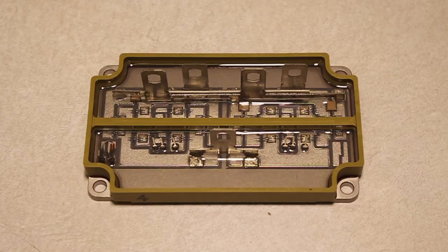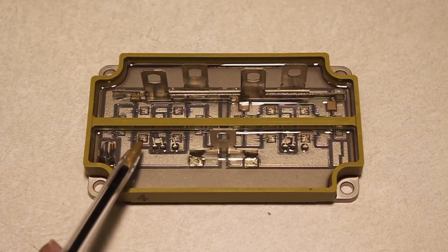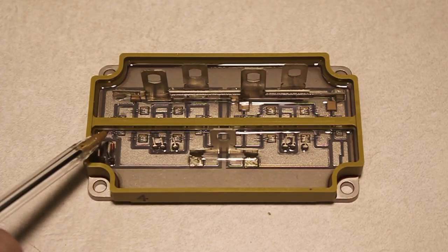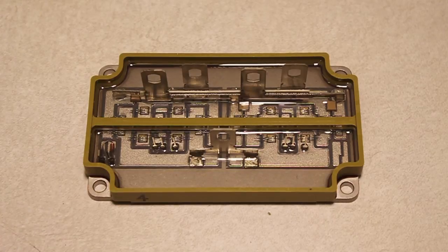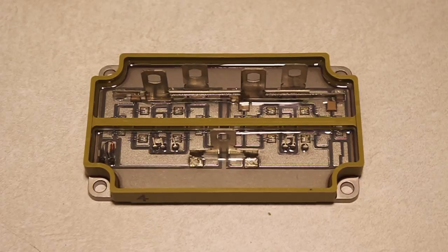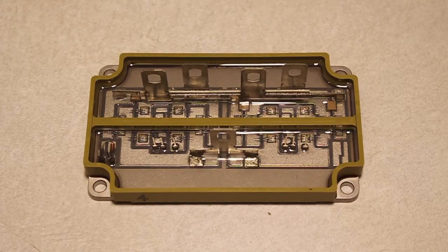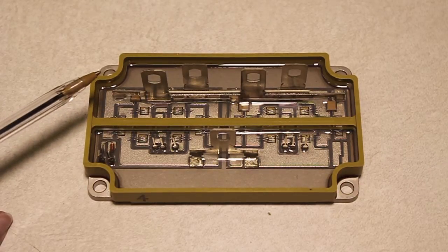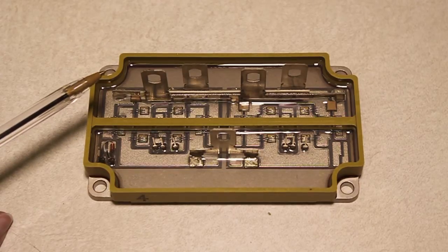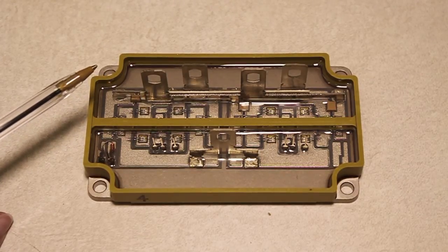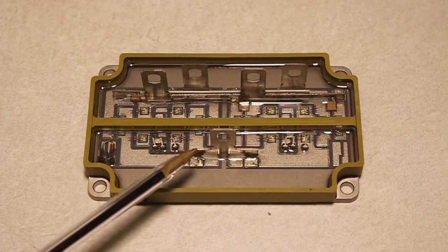This is a look at the 200 degree C 1.2 kV 120 amp silicon carbide half-bridge power module that was fabricated in our CPES packaging lab. 1.2 kV silicon carbide MOSFETs and Schottky diodes were used in this power module due to their high temperature and high speed capabilities. High lead solder was used for the die attach. In the back, we have the laminated DC bus bar, which uses Nomex for high temperature insulation. And on the other side, we have the AC power terminal.